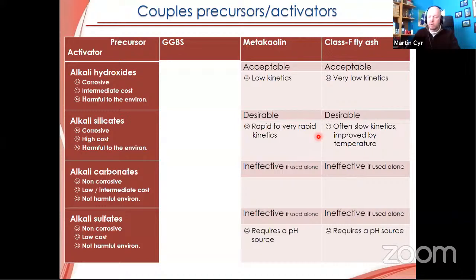It was said earlier, it works very well. I will not go further on that, but otherwise it can be much more difficult if we use these activators alone. Alkali carbonate and alkali sulfate, if we use them alone, will not work so well with metakaolin, of course. So the more we leave the calcium chemistry, the more difficult it is to make the formulation.